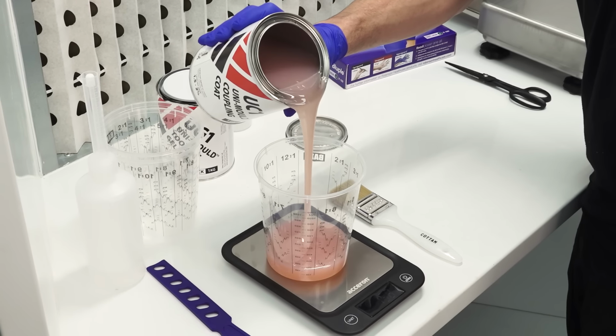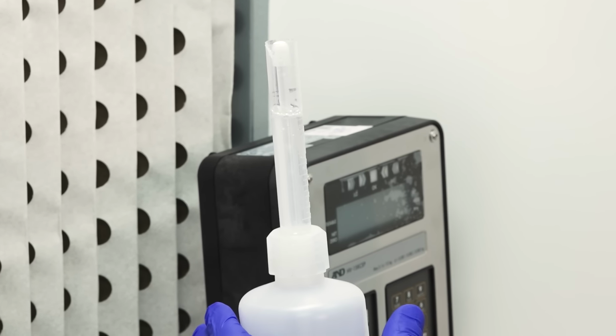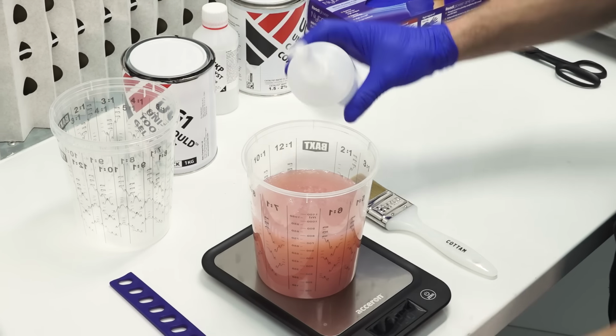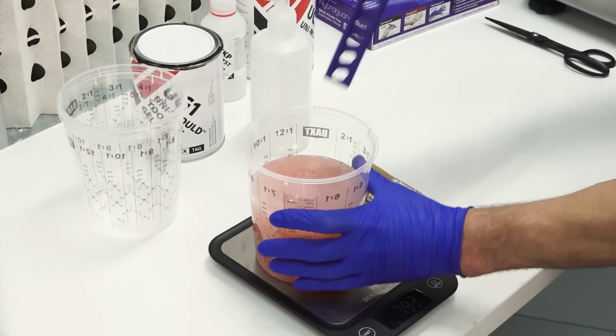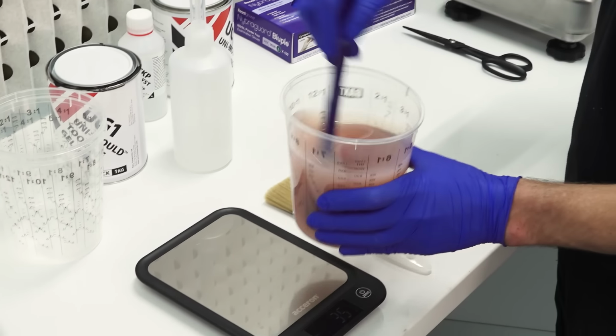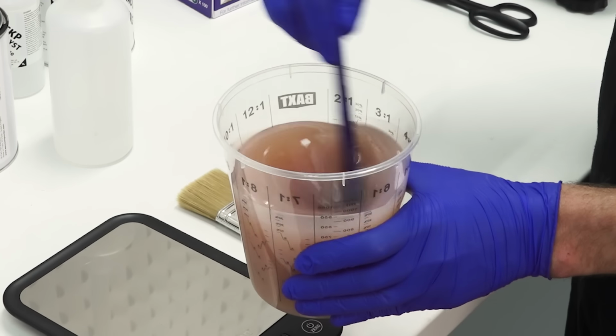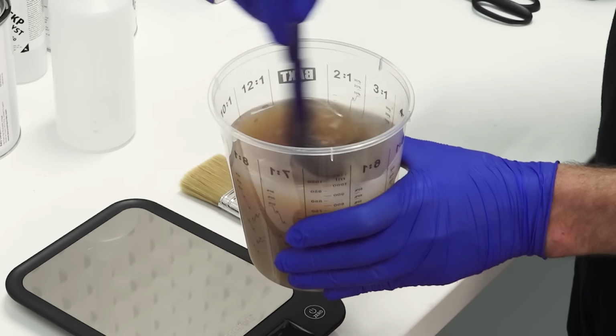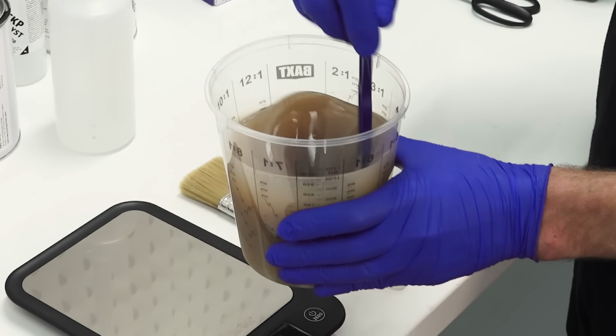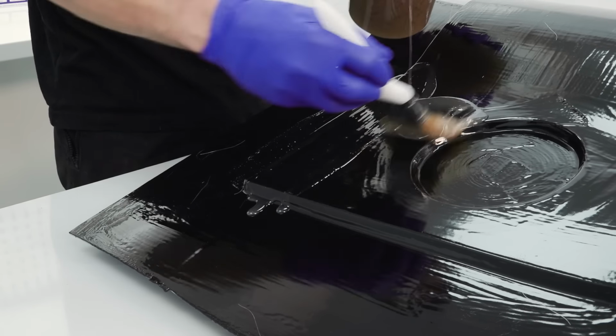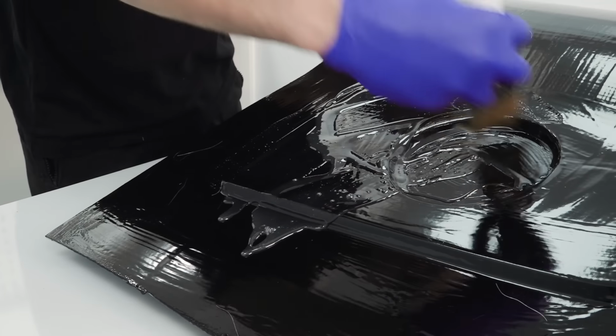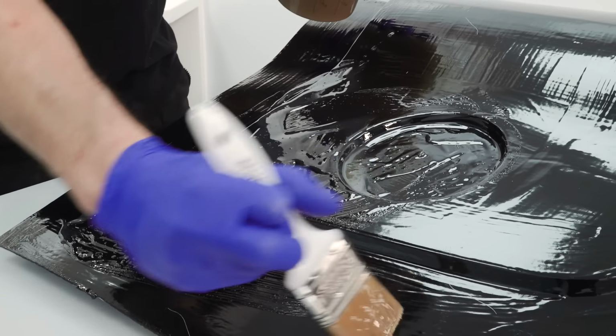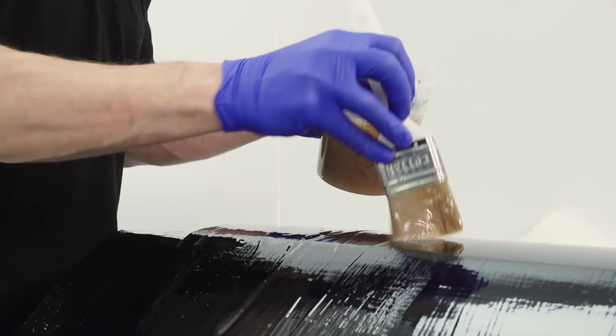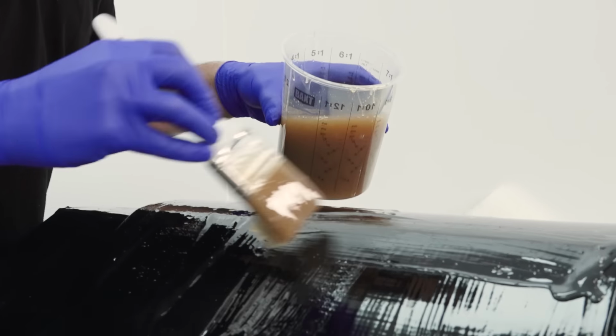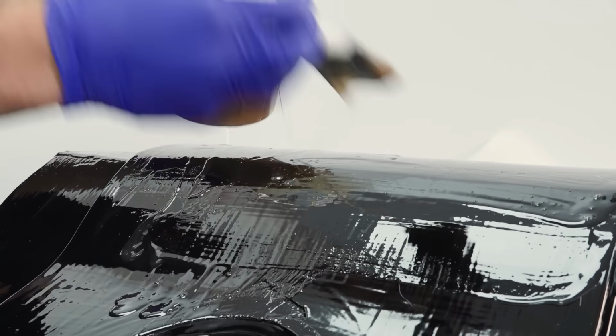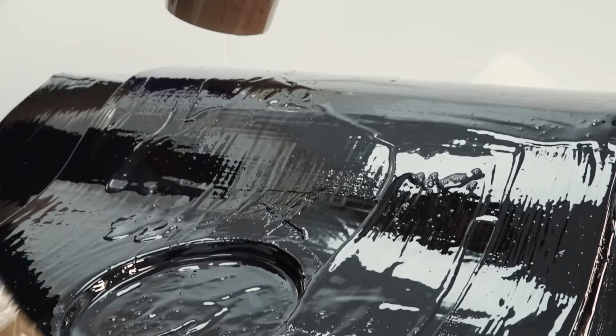The coupling coat resin can now be mixed with 1.5 to 2% MEKP catalyst. This resin is quite quick to cure, so I would typically use 1.5% unless it was a particularly small mould. You will need approximately 1 to 1.4 kilos of resin per square metre of mould surface. If your mould is larger than 1 square metre, then I would suggest mixing in batches of no more than 1.5 kilos at a time to ensure that you have sufficient working time within the pot life of the resin.